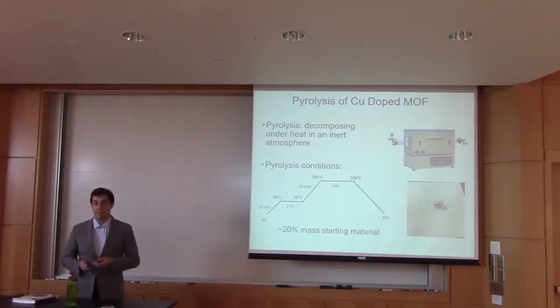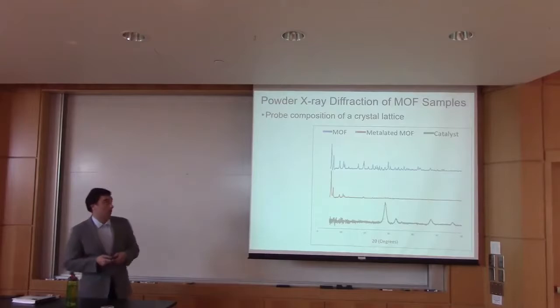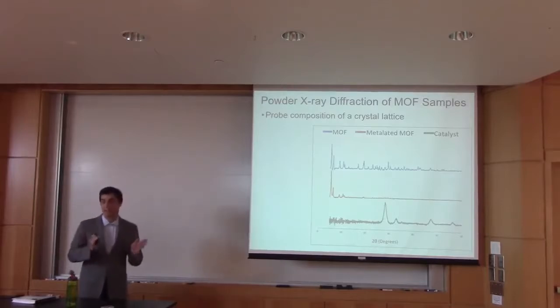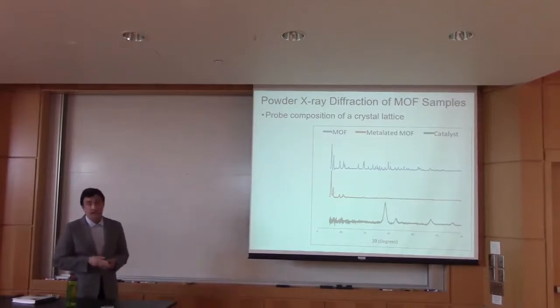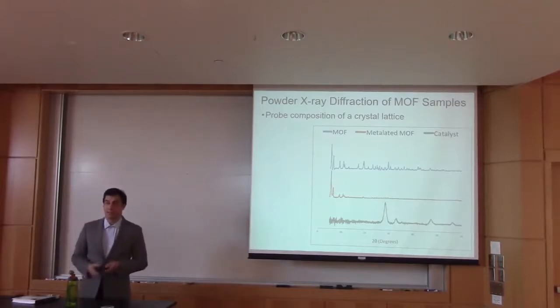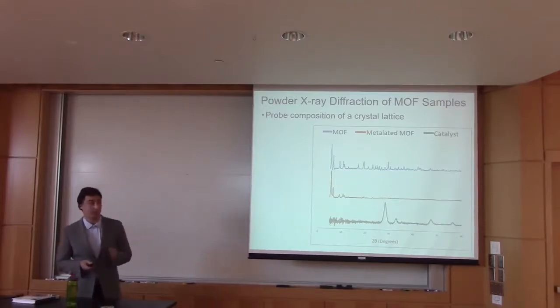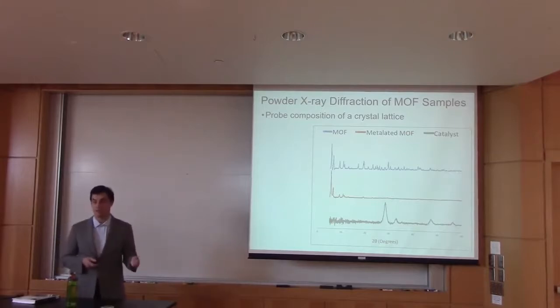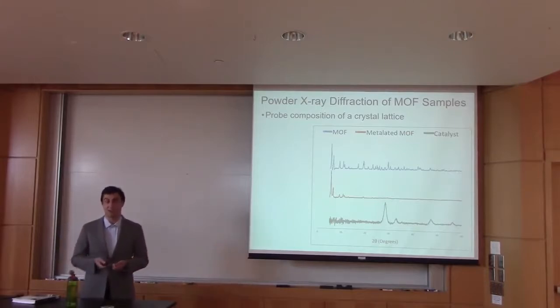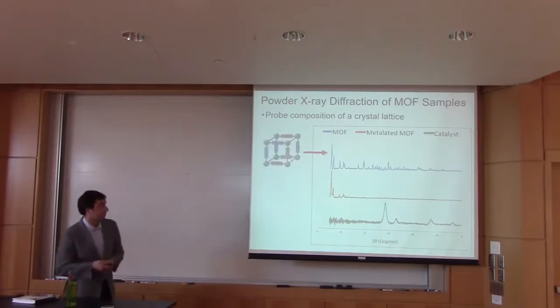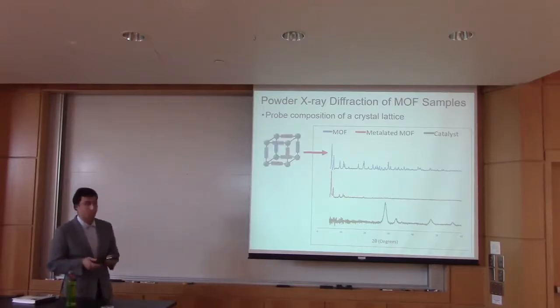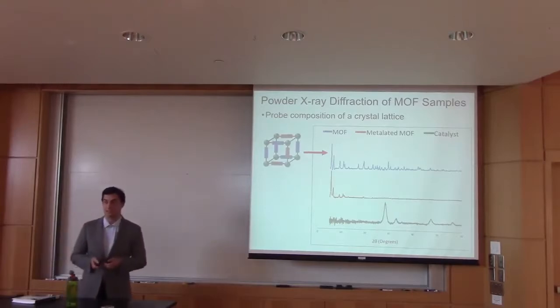From here, we need to characterize the MOFs and make sure what we're doing is repeatable, so we turn to a technique called powder X-ray diffraction, where we're using X-rays to probe the crystallinity of our sample. I use this as just a fingerprinting technique. The person who was working on this project before me, Dr. Jacqueline Brandt, was a crystallographer and did a lot of the legwork for this project, so I just had to compare it to my previous work and her work to check I was repeating the synthesis properly. This initial blue line is our MOF precursor. What we see is all of these nice peaks, which indicates a crystalline structure.